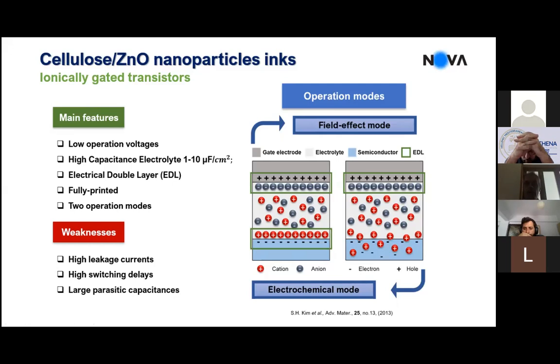Even with a very small voltage, you can accumulate a high density of negative charges in the semiconductor. So you can modulate the conductivity in the semiconductor, near the interface with the electrolytic membrane. You can modulate the conductivity of the semiconductor by several orders of magnitude by applying a voltage window of 1 or 2 volts. This is very interesting.